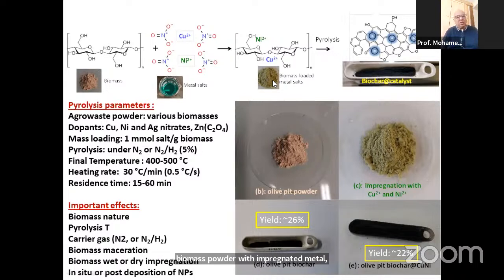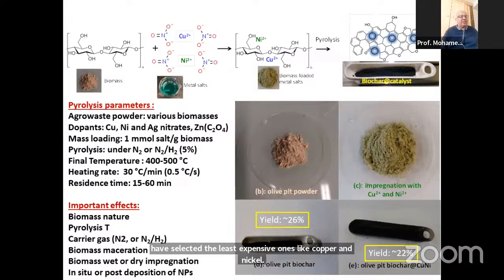We can have, for example, copper, nickel, silver. We can have a combination like copper-nickel, or silver-copper. And of course, you can have a large series of metal ions that you can load on the biomass before pyrolysis. Anyway, we have selected the least expensive ones, like copper and nickel salts. We also have silver nitrate, but we also work on zinc acetate to provide zinc oxide, because we are also interested in photocatalysts like zinc oxide.